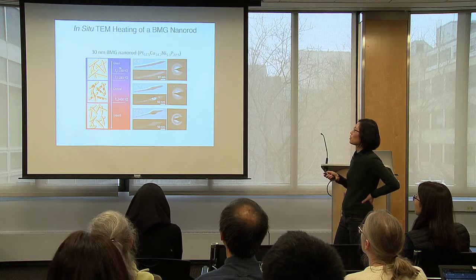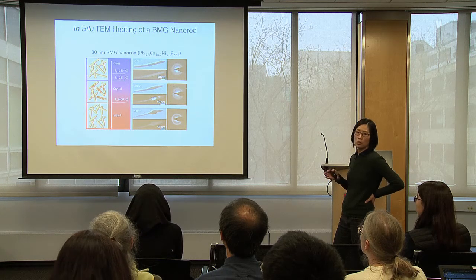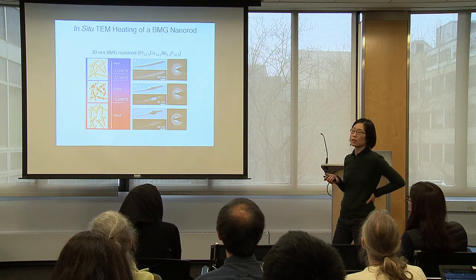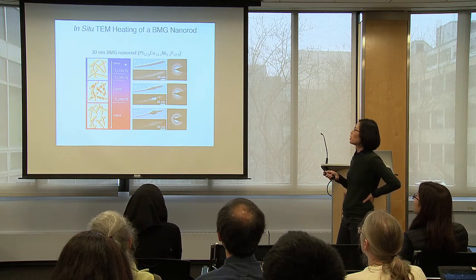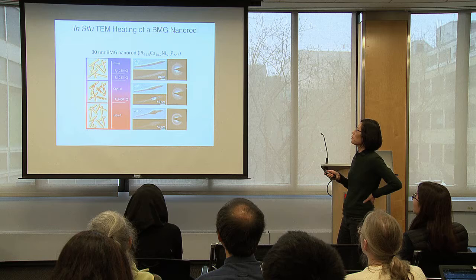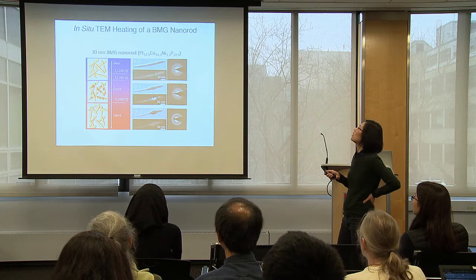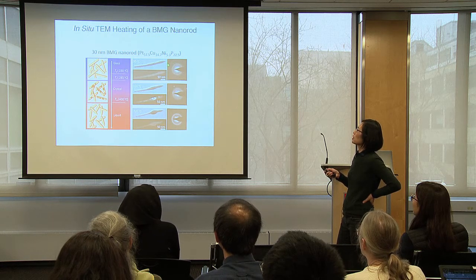So here's one particular rod. I'm using a regular TEM, not an aberration-corrected TEM. Here's a bright field image of one rod at room temperature. This is in dark field. I'm just randomly putting my objective aperture somewhere.